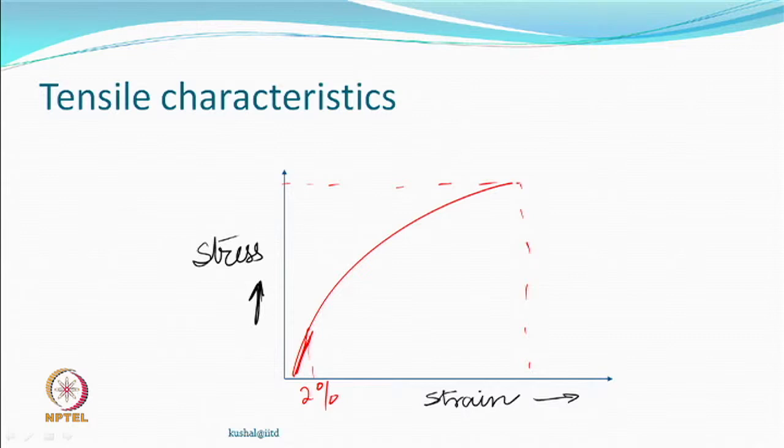Tensile strength should be measured carefully because the loss can be quite high. This test is performed on a standard tensile tester. Unlike false twist texturing where characteristics are measured after decrimping — where sufficient load is applied to decrimp the yarn before testing — in air jet texturing you simply need to ensure the yarn is held straight and not loose before testing.